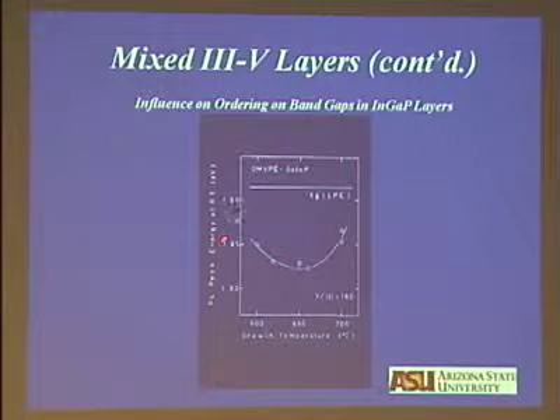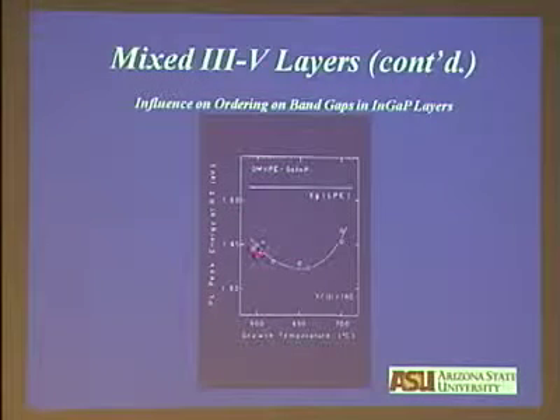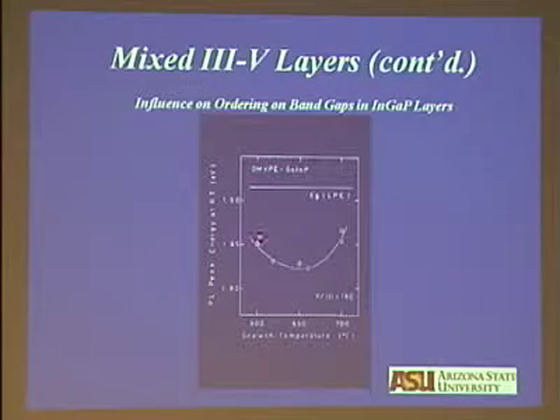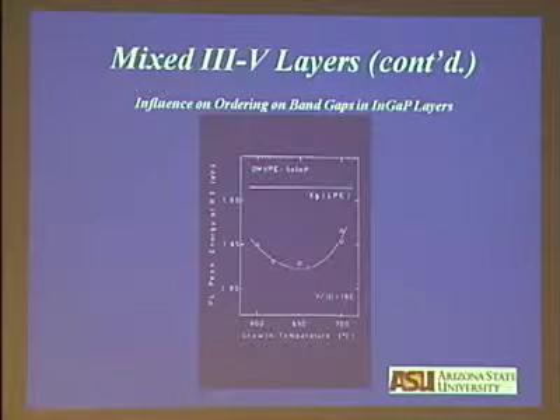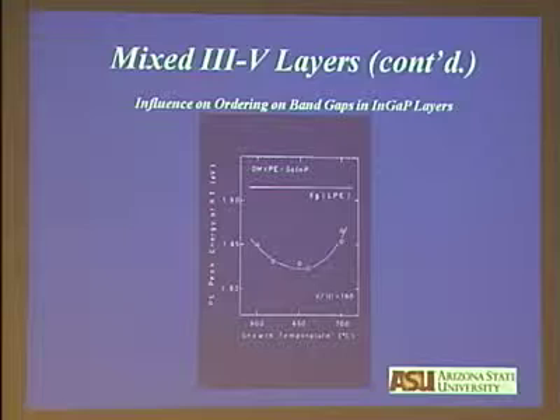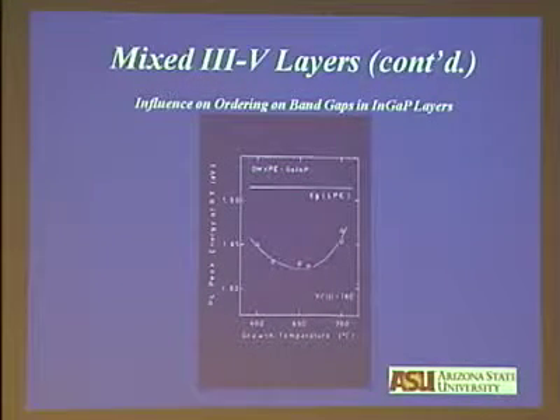What they observed is that at low temperature growth, the band gap doesn't change very much. As you increase the growth temperature, you reach a minimum in the band gap, and then at high temperature it goes back up again. The idea is that at low temperature, the temperature is too low to reorder the atoms. There is an optimal value where you can get the maximum order, and then when you grow at higher temperature, you get defective order.